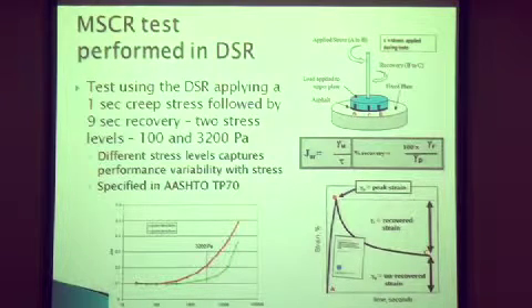So it's a low level of stress, not too dissimilar to the level of stress that you would use in that original Superpave specification, measuring G star divided by sine delta. This higher level of stress is significantly higher. You're going very much into a non-linear region of stress. And what you're doing here is saying to that binder, look, sample of asphalt binder or bitumen, are you strong at this stress level?